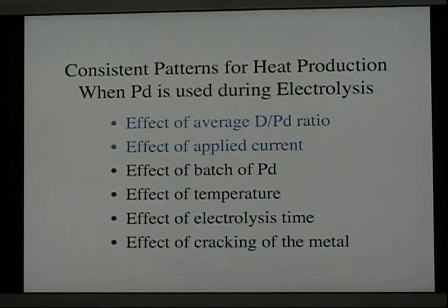And finally, palladium, when it takes up deuterium, cracks. These cracks make it very difficult, or prevent, the palladium from achieving the high deuterium to palladium ratio. When people have now found ways of treating palladium so that it does not crack, the success rate has improved dramatically.